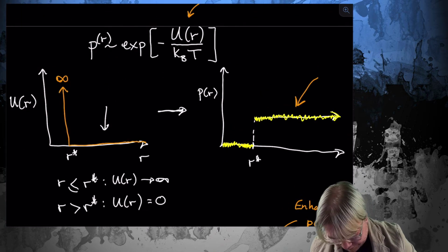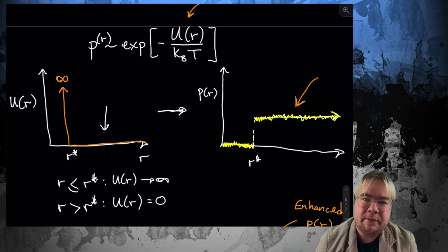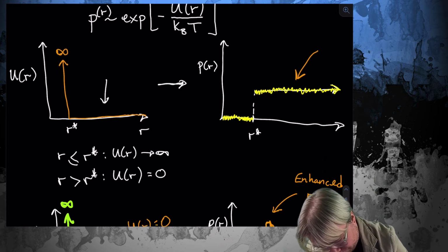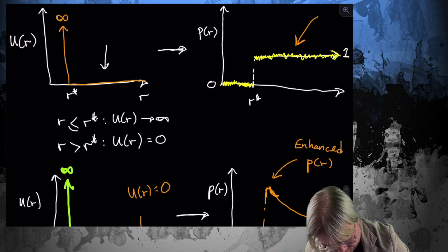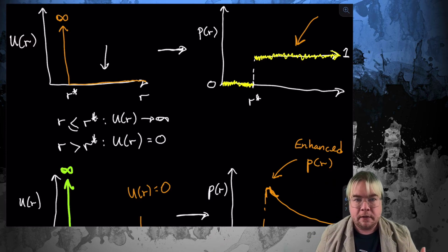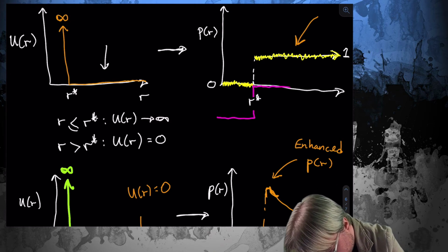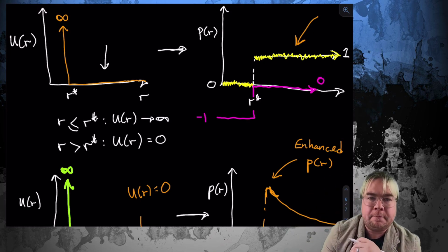Well, let's look at this. If I look at the probability of particles being a certain distance from each other in the case of the hard sphere limit, then if I subtract 1 from it, the function is 0 here, and the function is 1 here. So if I draw in the function, let's pick this bright color, that function minus 1, so P of r minus 1, is the Mayer f function, and it will look like this. So it's minus 1 here, and it's 0 out there.